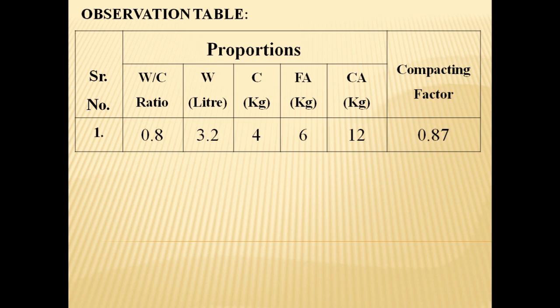Now we are going to see the observation table, which indicates proportions of water cement ratio, water, then cement, then fine aggregates, coarse aggregates, and compacting factor. So as per observations, for water cement ratio of 0.8, we have got the value of water which is 3.2 liters. For M20 grade of concrete of proportion 1:1.5:3, we have got cement equal to 4 kgs, fine aggregate equal to 6 kgs, and coarse aggregate equal to 12 kgs. So finally, for water cement ratio of 0.8 and M20 grade of concrete, we have got the compacting factor of 0.87.